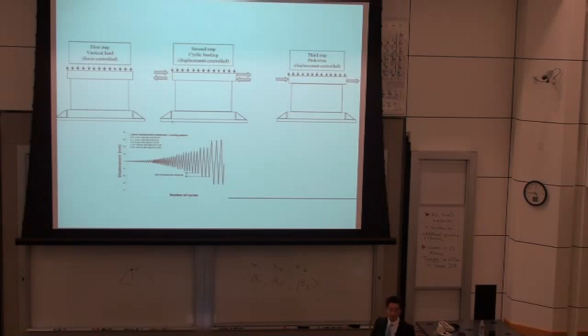You apply a so-called vertical stress level, and then you have a time history or loading history where you do the cycle 3 times in each direction, and if the hysteresis is closed, then you go up to the next higher step. So I will show it to you afterwards. It will finish when the full masonry is broken, or normally when 80% of the maximum horizontal force is falling down.